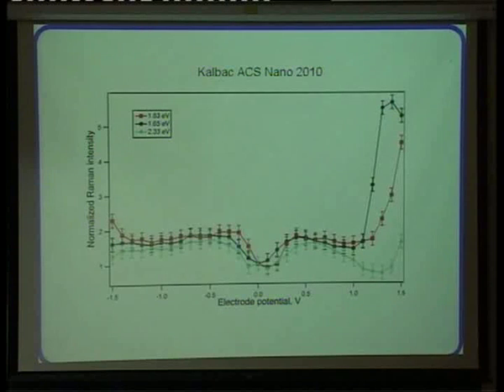In fact, there was in 2010 an example from the group of Dresselhaus where they measured the Raman intensity, and they saw, quite strangely, that for a very high potential, this is the electrolyte doping, there was a very large increase in intensity, and that is quite unknown.